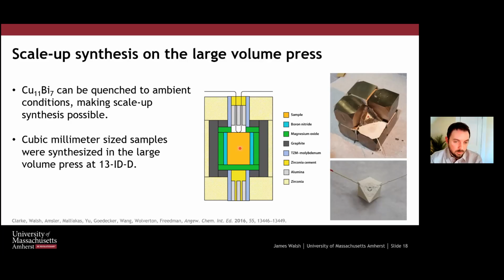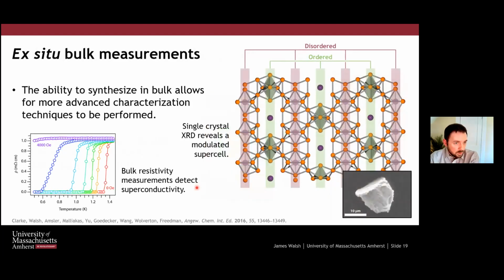And what's nice is that we create the copper bismuth, and it's quenchable. And so because it can be quenched, in other words, you can remove the pressure and still have that compound. It's not always the case. We usually hope that it is, but sometimes it just isn't. Because you can do that with copper bismuth, it allows us to do other measurements ex situ. So we can now take it away from the high pressure conditions and be able to do analysis that we can't really do in the diamond cell, or at least we couldn't. And so one of those is the measurement of its bulk resistivity. And when we do this, we detect actually that it's a superconductor, at relatively low temperature, 1.4 Kelvin. But this is something that we wouldn't have been able to determine otherwise in the cell.